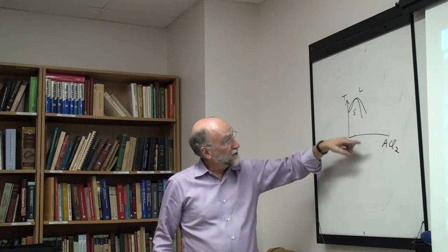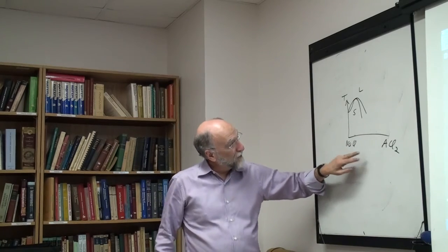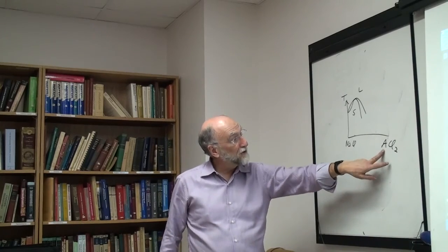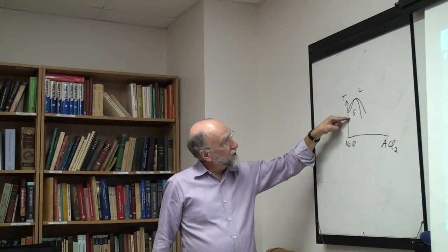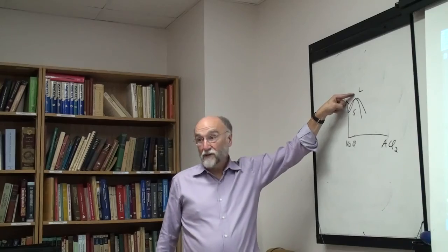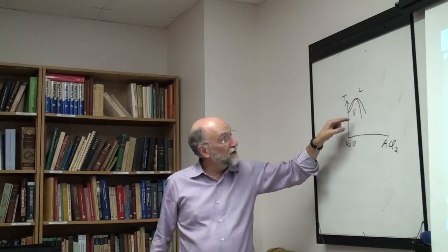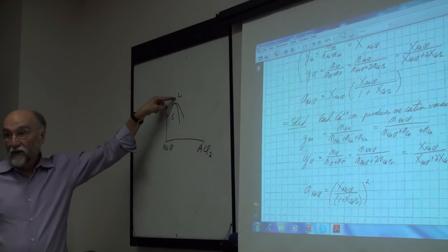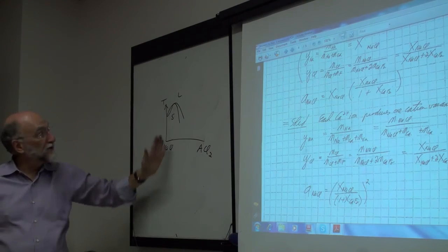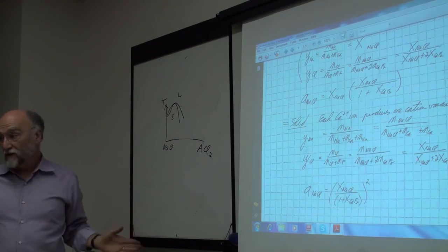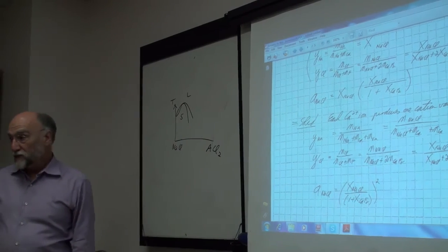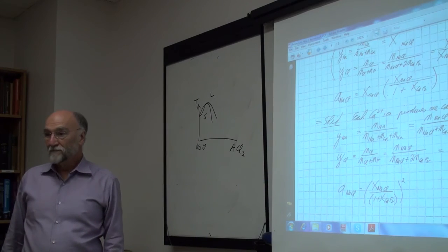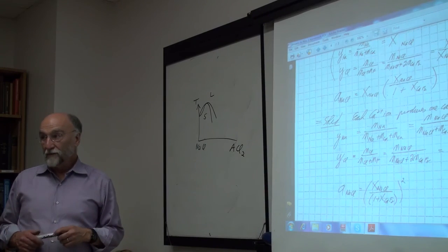So as you take sodium chloride and add this asymmetric salt, which has a different charge, and by introducing the vacancies, you're stabilizing the solid more than you're stabilizing the liquid. The entropy of the solid, because of this term here, increases more quickly than the entropy of the liquid of the same composition. So the solid is entropically stabilized relative to the liquid, so it tends to push up the liquid solid curve.